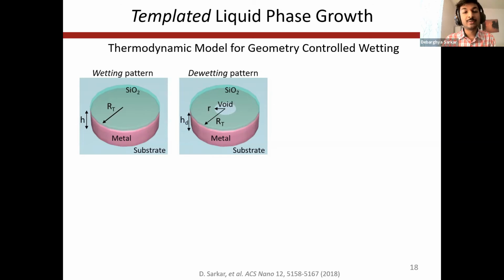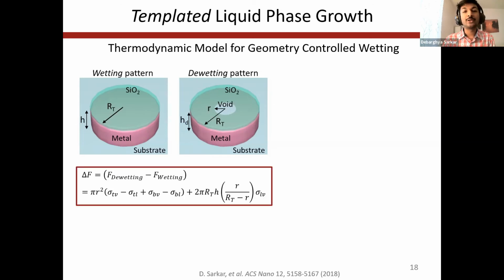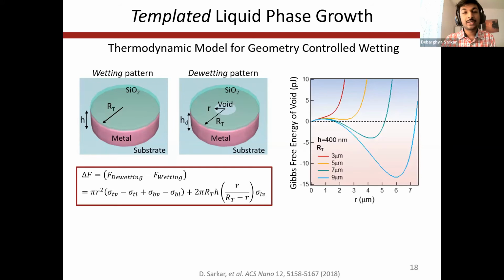And when we subtract the Gibbs free energy of one from the other, we get the Gibbs free energy of formation of void as a function of the void radius and the template geometry. And when we plot that as a function of the void radius, we see that for a given thickness of indium, which in this case is 400 nanometers, for templates of radius denoted as RT, so for templates of radius 3 micron and 5 micron, Gibbs free energy of formation of void is positive for all values of void radius.